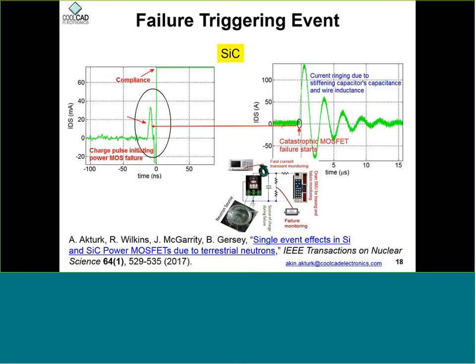So to find what kind of event causes failure in silicon carbide devices, we do transient tests. We try to capture the current bumps that are a result of these primary knock-ons or secondary knock-ons, and that causes a failure. On the right you can see we have this circuit. Once the device shorts, all the charge within that capacitor, which is called the stiffening capacitor, is dumped onto the device under test, and you can get tons of current flowing through the device.